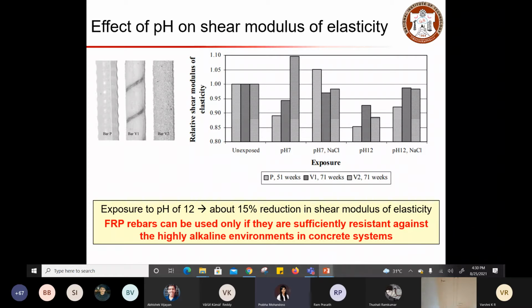Right. So the only concern that we have with FRP rebar is its performance in the alkaline environment. That is, basically the effect of pH could affect the properties of your FRP rebar. So especially when we say properties, it mainly affects the shear modulus of your FRP rebar. Right. So just to have a sense of how pH plays a role in affecting the performance of FRP rebar, here you can see different types of FRP rebar exposed to different pH level conditions. Here you have three types of FRP rebar.